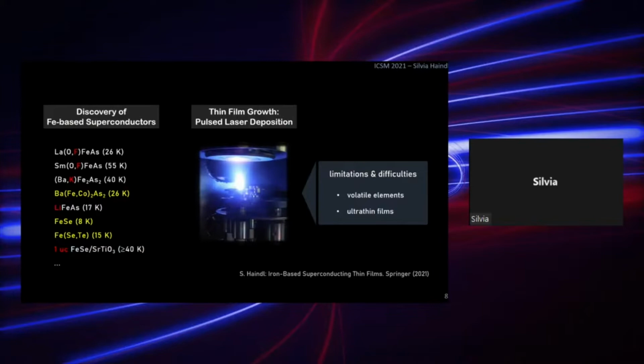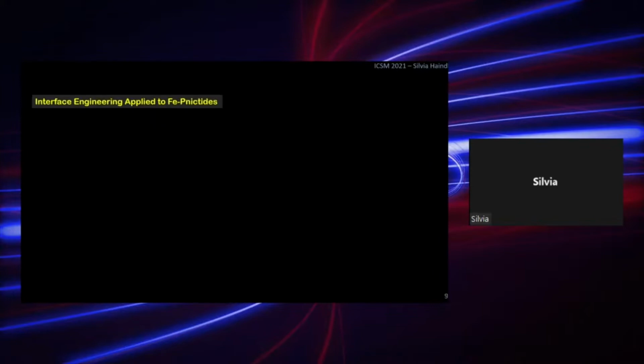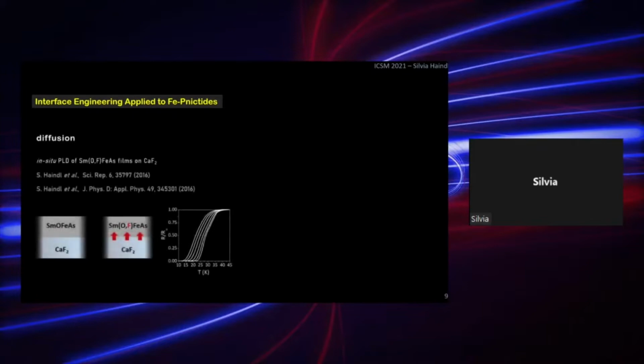There is no need to give up at that point because we can apply so-called interface engineering concepts also to the iron-pnictides. And in the past 5 years, there were mainly two advances within that field. One was using diffusion and bringing the so-called volatile fluorine from the substrate into the as-grown films in an in situ PLD process of the samarium iron oxypnictide thin film. And this was shown in 2016 and maybe in one of the previous ICSM conferences by me.